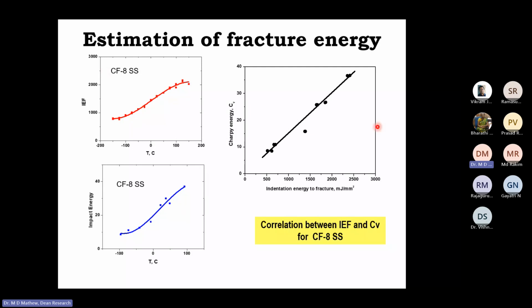Now this is a cross plot of these two graphs, the red and blue. The cross plot is what you see as the black one. On the y-axis, you have the Charpy energy determined from this graph, and on the x-axis, you have the IEF determined from this. You find that there is an excellent correlation between the Charpy energy and the indentation energy to fracture.